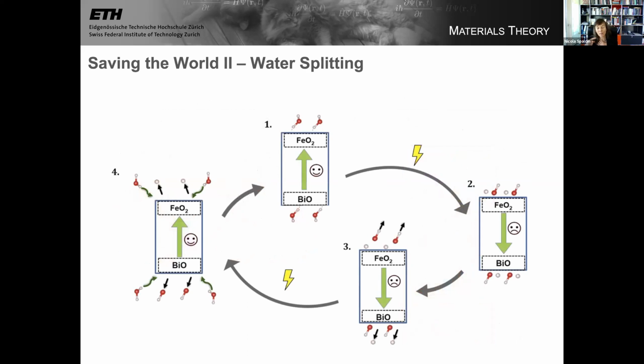So you could then envisage a cycle for effectively water splitting, in which when the bismuth ferrite slab is happy, water molecules adsorb on the surfaces. You switch it, for example, with an electric field, the water dissociates into the ions, and the positive ions stay on the negative surface, and the negative ions stay on the positive surface. So we have a very effective way then of splitting the water into its constituent ions.